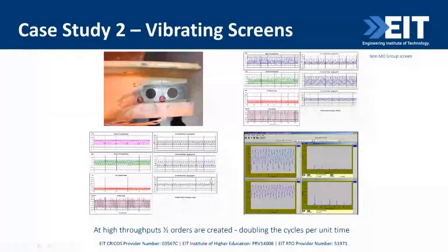So just be careful, finally, of half orders on your screens. If you go too fast, depending on your ore feed, obviously, depending on your deck shape, on your deck flexibility, stiffness, the whole thing. If you go too fast, you can excite half orders, which is obviously going to double your cycles in a unit time. I'd be careful of that. Make sure you're not exciting higher harmonics.